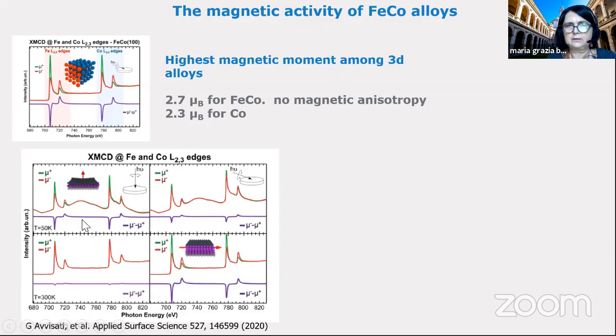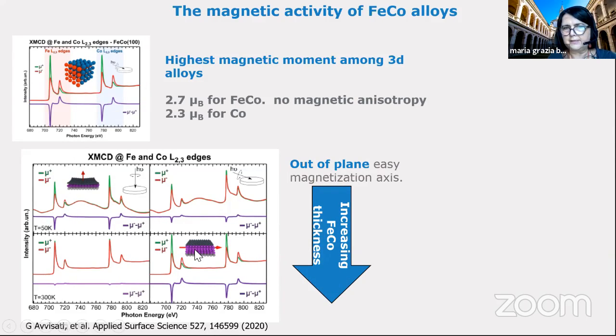That is the experiment looking at iron and cobalt absorption. And also in this case, if you have a single layer, you will have a higher contribution at normal incidence and a lower contribution at grazing incidence, as we saw for cobalt. So the easy magnetization axis will be out of plane. And when we increase the thickness, we have a switch. Also in this case, the signal is very, very low here, but if you switch the magnetic field, you will have a very intense dichroism, and so the easy magnetization axis will be in plane.